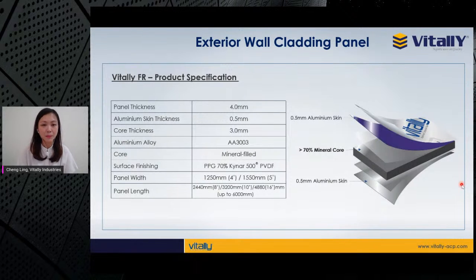The total thickness of the panel is 4 mm. The aluminum skin is 0.5 mm, two layers of skin, and the remaining 3 mm is the core. For the aluminum alloy, we use AA3003, and the core is mineral filled core for the FR panel. For surface finishing, we use PPG coating. For the sheet size, our standard width is 4 feet, which is 1250 mm, and we can supply 5 feet upon request. For panel length, we can produce up to 6 meters, about 20 feet, but our standards are 8 feet, 10 feet, and 16 feet.